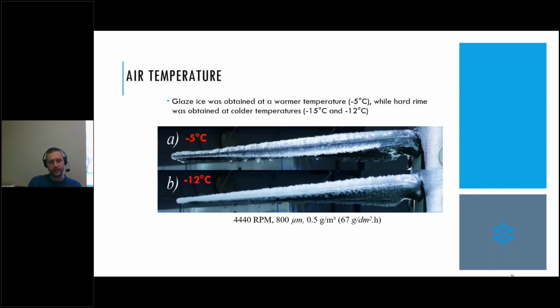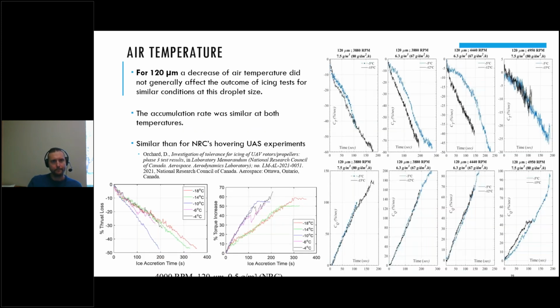So the first thing that we observe is that more of a glazed ice was obtained at warmer temperatures at -5 Celsius degrees, so a clear glazed accumulation, while for the colder temperatures, we obtain more of a hard rime accumulation, more of a white ice. Next slide.